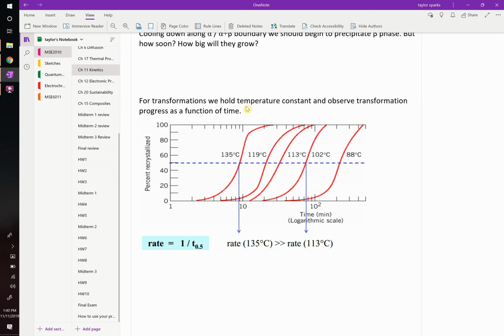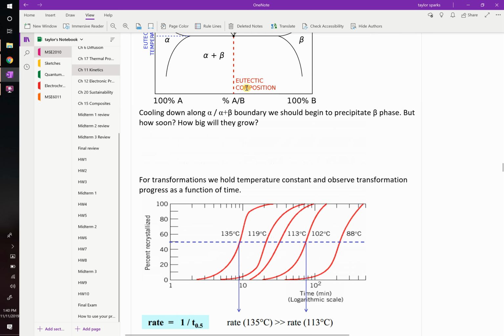Essentially, they all concurrently realized we can model transformation if we have the right mathematical expression. They know the following: that things start to transform, and if you look at your percent, say, for example, in crystallization of a polymer, it starts to transform really slowly. The rate is slow. Then once it's transforming, it reaches a maximum rate, like the slope here is at the highest. And then once it transforms, it starts to slow down again. Basically, this describes the vast majority of transformations, right?